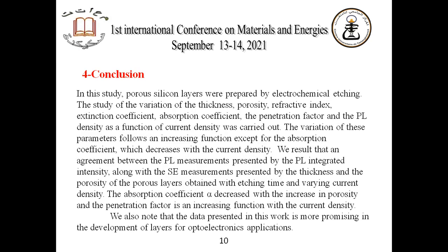Finally, the conclusion is: in this study, porous silicon layers were prepared by electrochemical etching. The study of the variation of the thickness, porosity, refractive index, extinction coefficient, absorption coefficient, the penetration factor, and the PL density as a function of current density was carried out. The variation of these parameters follows an increasing function except for the absorption coefficient, which decreases with the current density,